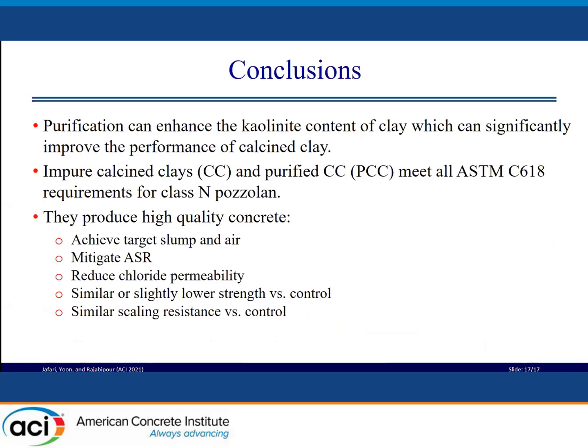In conclusion, purification can enhance the kaolinite content of clay, which can significantly improve the performance of calcined clays. Impure calcined clay and purified calcined clay meet all ASTM requirements for Class N pozzolan. They could produce high-quality concrete with target slump and air content, mitigate ASR, reduce chloride permeability, and show similar or slightly lower strength versus control, with similar scaling resistance versus control.